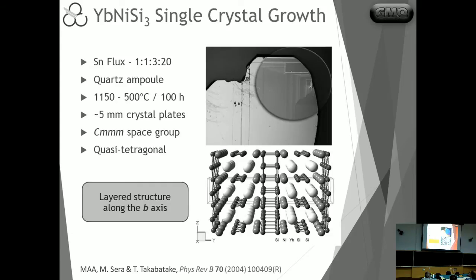All right, so back to about 15 years ago, I was a fresh new postdoc in Hiroshima University with Professor Takabatake, and one of the topics that I picked up there to look at was to try to work on these rare earth nickel silicon 3 systems. And luckily for me, in the very first attempt that I tried to grow a single crystal of this compound, we absolutely didn't know anything about them at the time, and the beautiful crystals just grew right away through the flux method. This crystal here, there's no length scale here, but this is actually the contour of a quartz ampule. So this is a pretty large plate-like crystal that grew immediately.